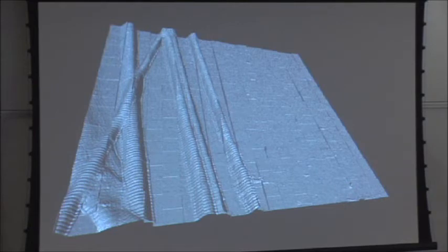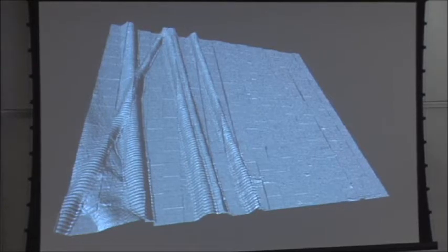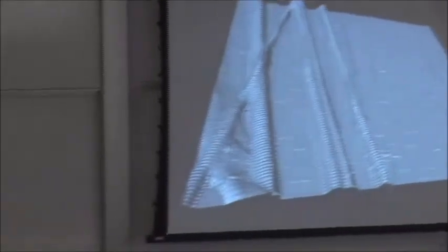So now we have a way with a closed loop stage to scan very large areas up to a centimeter and collect data at about 2 nanometers resolution. So that opens up a lot of possibilities in material science. And then Lorena and another student, Ollie Payton, came up with the idea of using contact resonance at high speed.